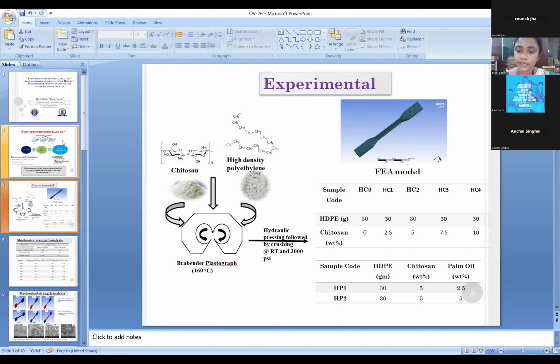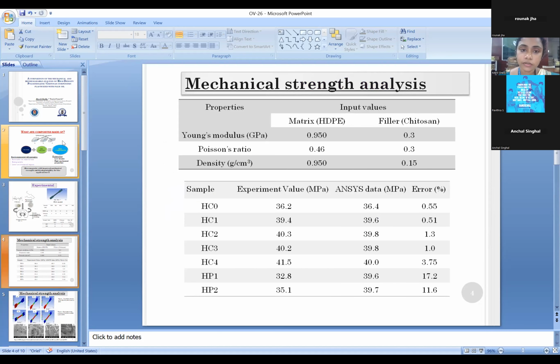of mechanical strength. To the composite having high strength, I have added various concentrations of palm oil, 2.5% of palm oil and 5% of palm oil. These are the two sets of composites which I have prepared, and I have taken them for the mechanical strength analysis. The mechanical strength has been studied by using tensile strength measurements. It was observed that with the addition of chitosan, the tensile strength of the composites was increasing, which indicates better interaction between the chitosan and the high-density polyethylene.